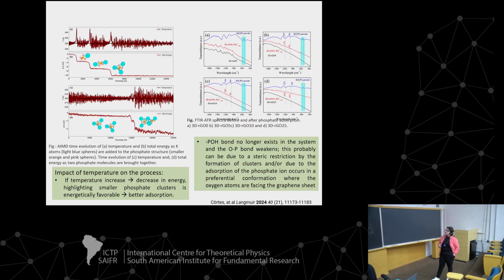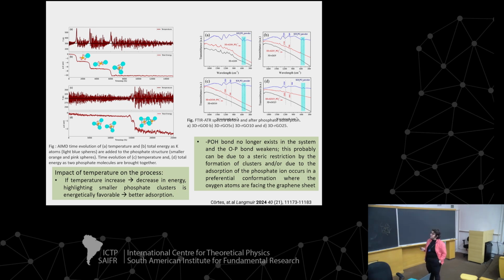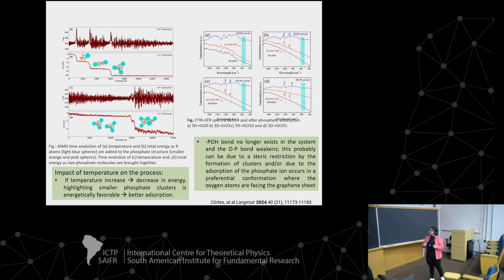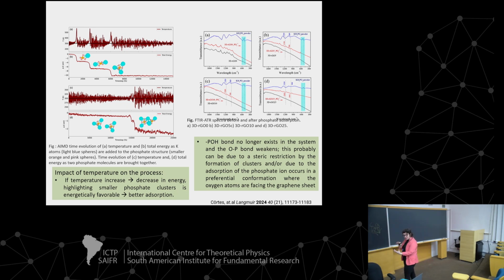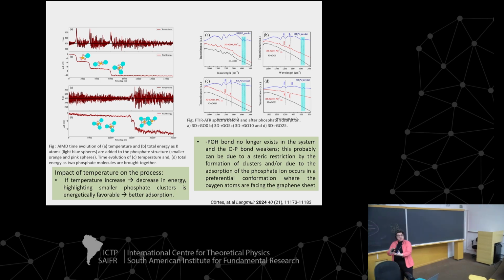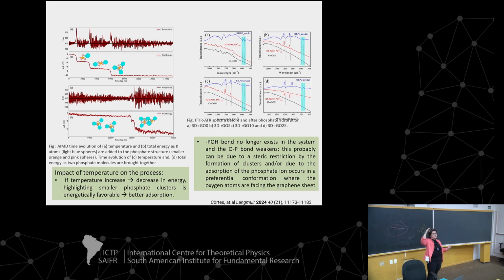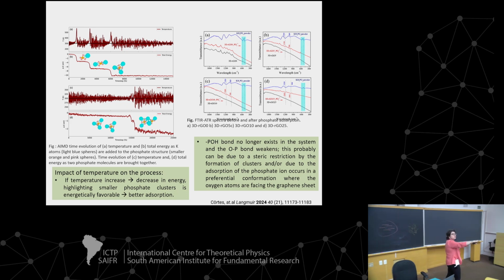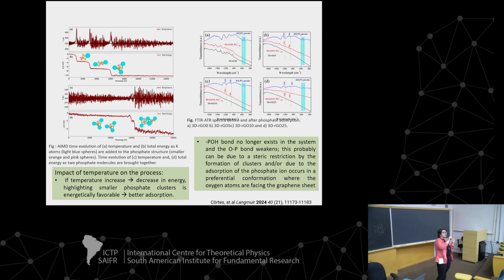Also, we use DFT calculations, and we see the impact of the temperature, and in agreement with the experimental data, we saw that the decrease in energy highlights the smaller phosphate clusters, and the adsorption is energetically favorable. So if we have a higher temperature, we avoid this aggregate formation, and we can enter in the pores and keep adsorbed in the sheets.